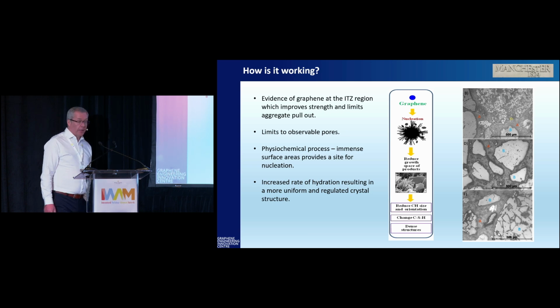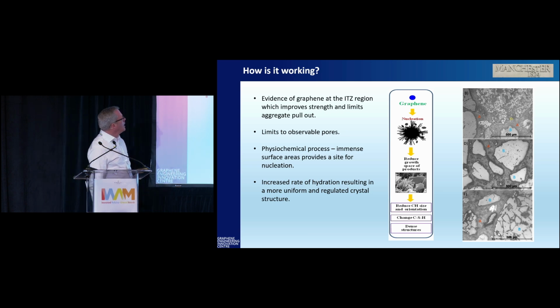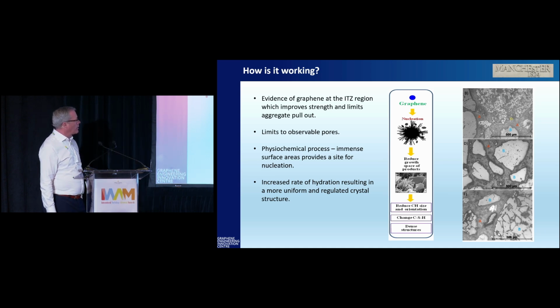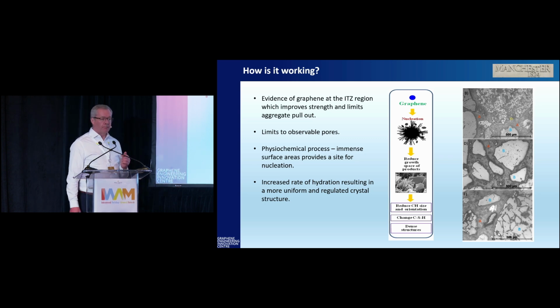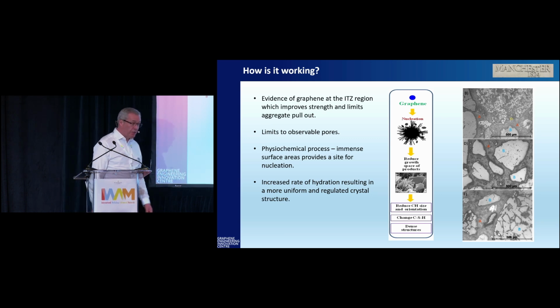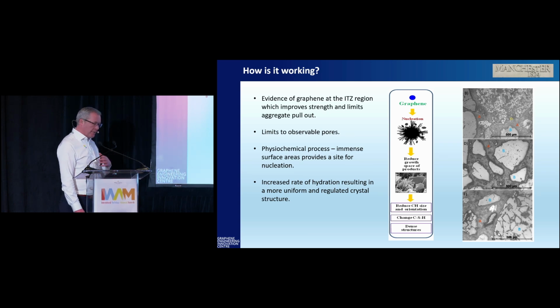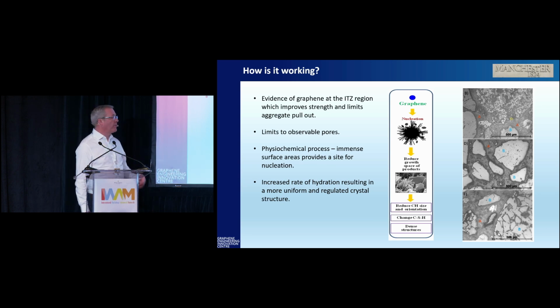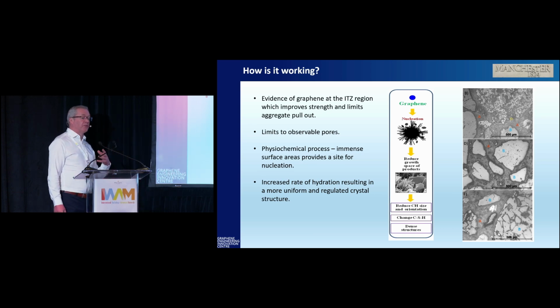So how does the mechanism work? There's lots of modeling, but largely if you look at the interface zones, which is really between the aggregates and the cement, we're actually starting to show that if you can map the dispersion of the graphene, whether it's done by dry or done by liquid, appropriately, we can actually start to see. So we're working with the University of Manchester's electron microscopy facilities, and we're doing a lot of cross-sectional sampling to understand the mechanism more. But there's still quite a lot of quantification that's got to be done. Certainly about how we can improve hydration, how we can improve mobility during the mixing processes. I say cementitious systems, it's an intensely physical chemical process, and we're trying to use the graphene and its immense surface area to provide additional nucleation points. So it's quite a difficult process to try and quantify once you've actually got it cast.